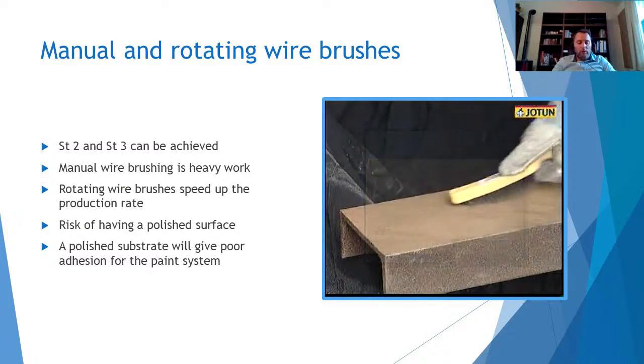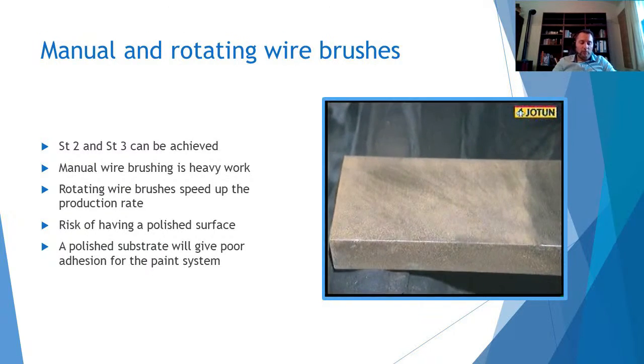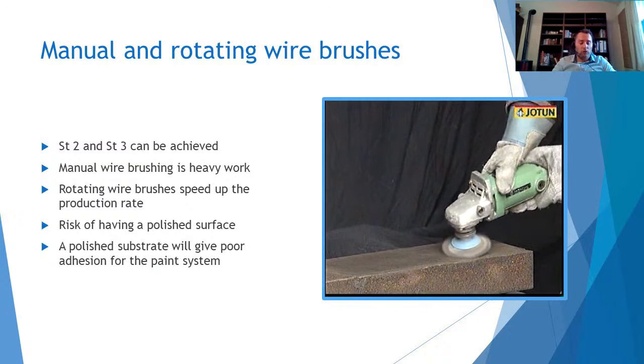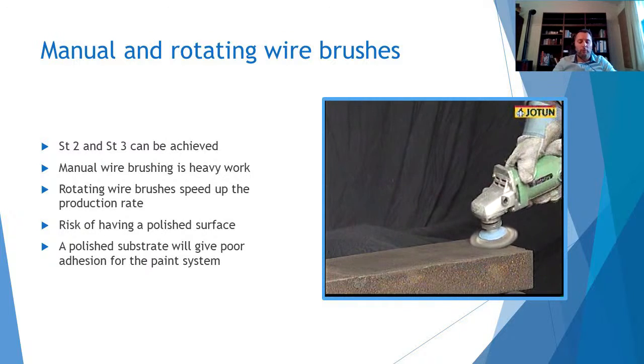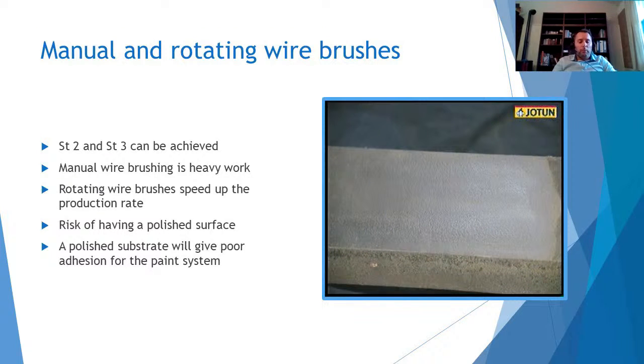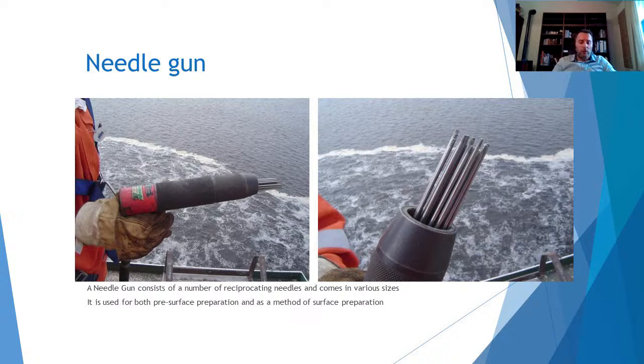Rotary wire brushes are available in two general types, straight in line or vertical right angle. Overworking the surface with a wire brush can be detrimental because excessive burnishing develops a polished surface, which means a poor anchor profile for most coatings. Another instrument used as power tool cleaning is the needle gun or needle scaler. It consists of several hardened steel rods that vibrate against the surface. Needle scaling is slow, similar to other power tools. It burnishes while producing a relatively clean surface, but in this case it produces a surface profile. Needle scalers are effective on welds, corners, and irregular surfaces.